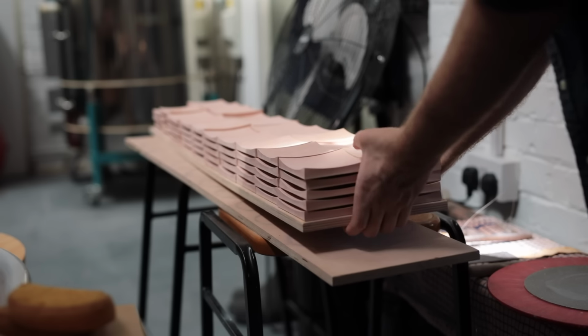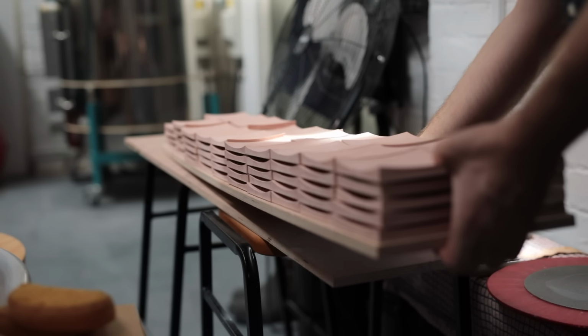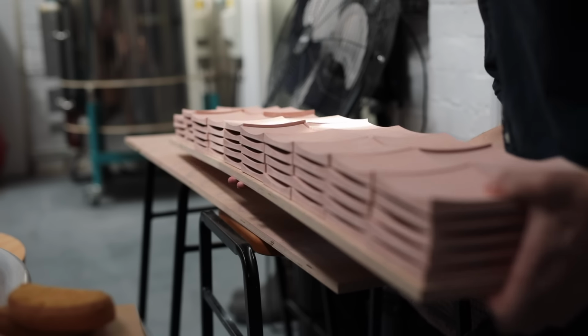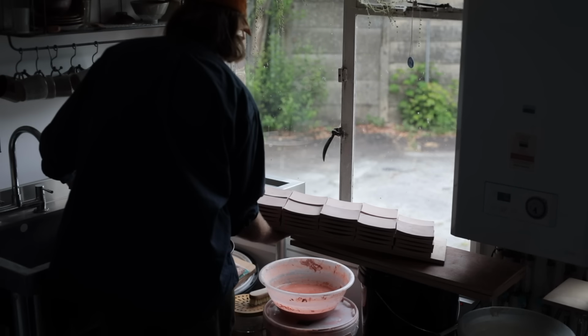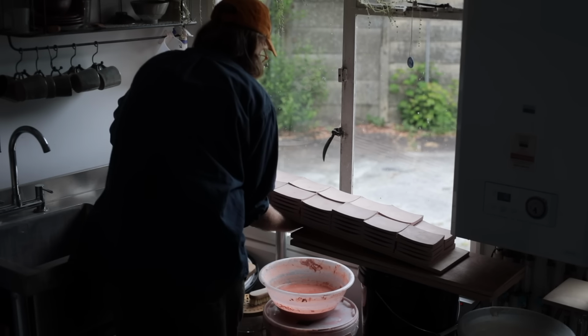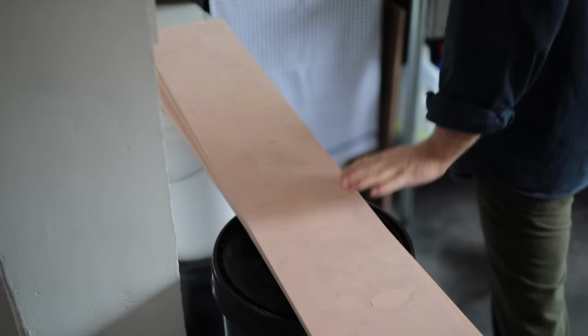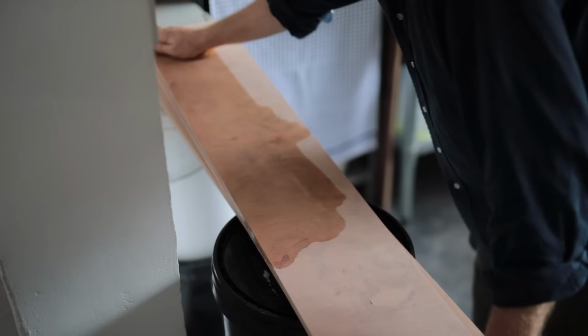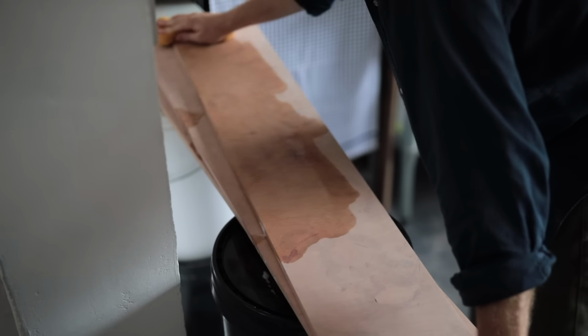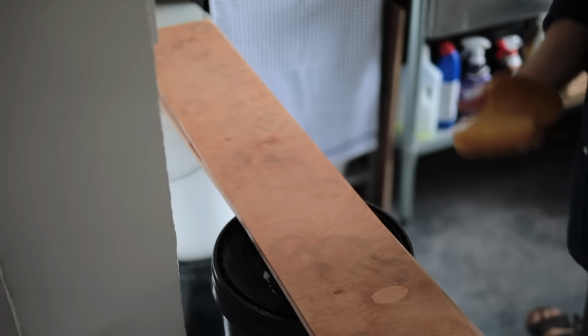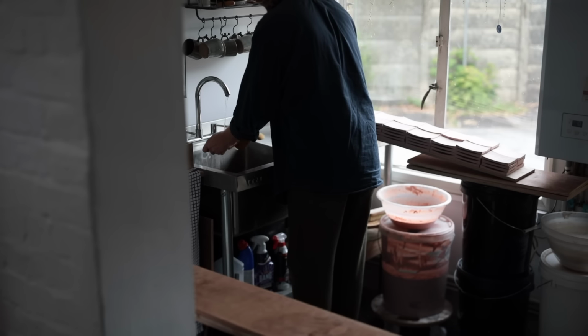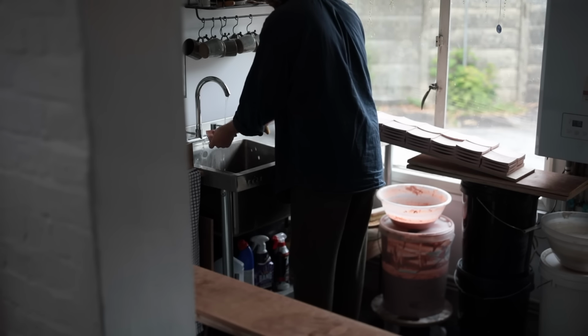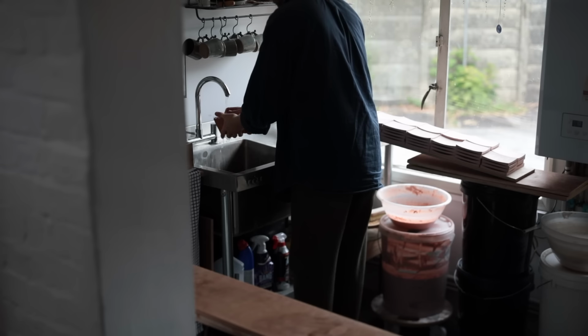Now, the only annoying thing about this process is that it left each dish relatively dusty. In fact, in some cases the dust was really caked on and hard, and I absolutely cannot glaze these until that dust has been removed. As if I did leave it and then I dipped each of these in glaze, they would probably all do something called crawling, which is when the glaze that coats these begins to separate from itself, leaving random patches of bare clay messily across the dishes. In short, it would ruin them.